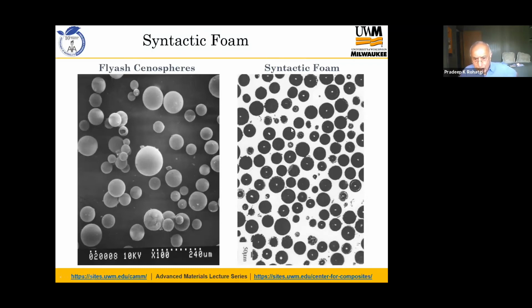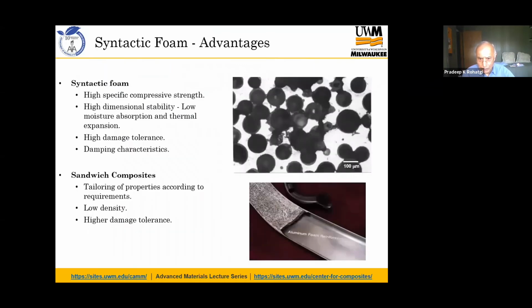We have used pressure infiltration to incorporate these hollow particles of fly ash in the matrix of aluminum, which is white. So this is a 60 volume percentage hollow microsphere embedded aluminum. We call this syntactic foam. It has a density much lighter even than aluminum, about 1.4, and its energy absorption per unit weight is better than that of steel. So it is being thought of to be used in cars to prevent injury due to crashes and also for armor applications.